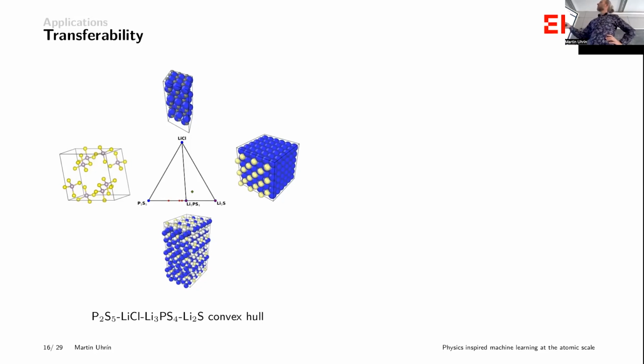So the first thing I asked you to do is take, if you look at this convex hull, the green dot is kind of where we're at with our crystal structure. So you can see it's not fully stable. It's a little bit up in formation energy, but low enough that you can stabilize it reasonably easily. So I asked you, can you run molecular dynamics on the phases that are at least around our point and this final one? Can our model capture these systems correctly? And I thought the answer would be no. But in reality, he said, oh no, these three on the right, we can run molecular dynamics, no problem.